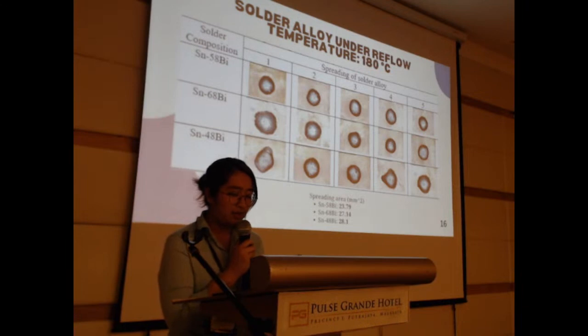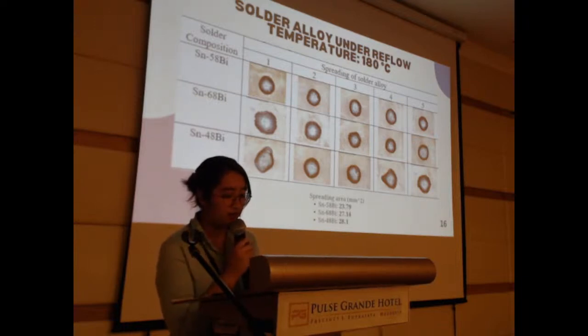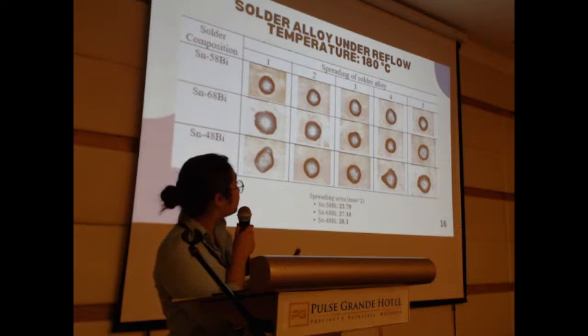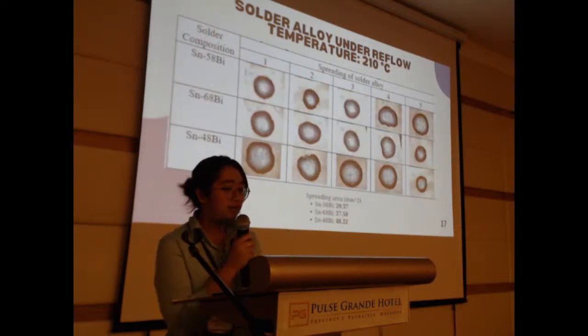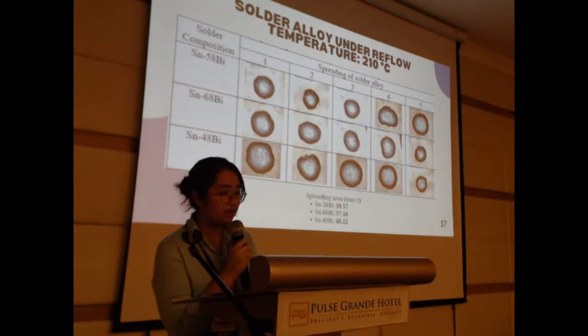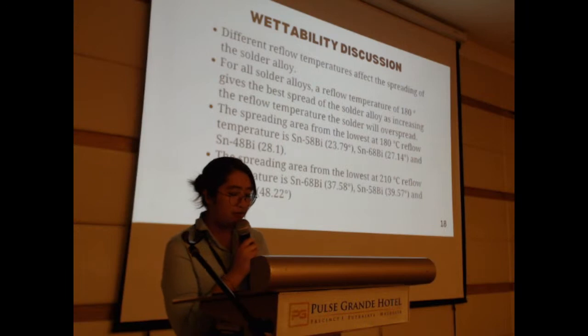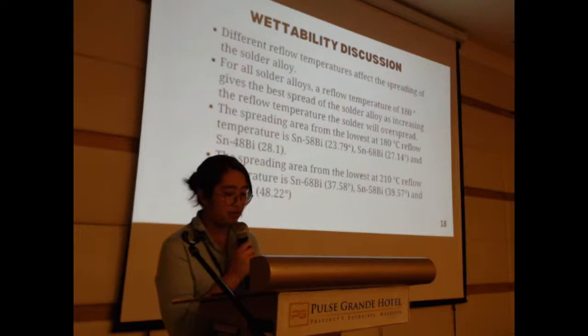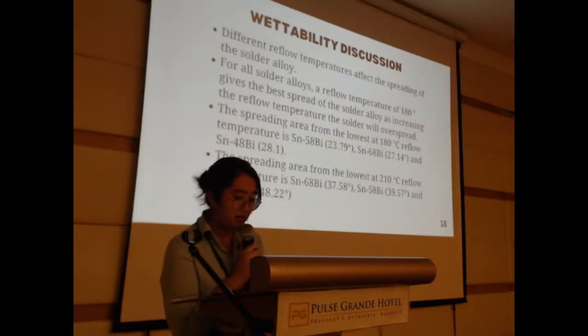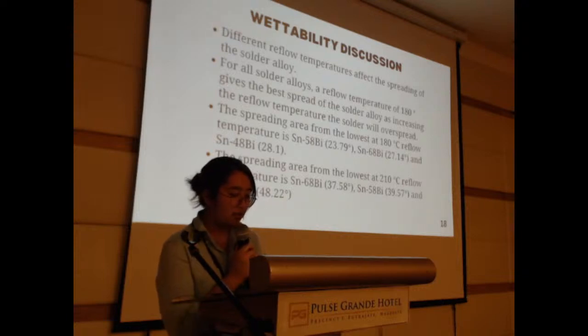So this is the wettability results. I used 3 different bismuth compositions as previous, but under the 2 different reflow temperatures. So here is for the 180 degrees Celsius, and here is for the 210 degrees Celsius. And as you can see, for 210, the spreading area tends to be bigger. So from this, I can deduce that different reflow temperatures do affect the spreading area. So from here, we could see that 180 degrees gives the best spread as compared to 210 degrees, because 210 tends to overspread the solder.